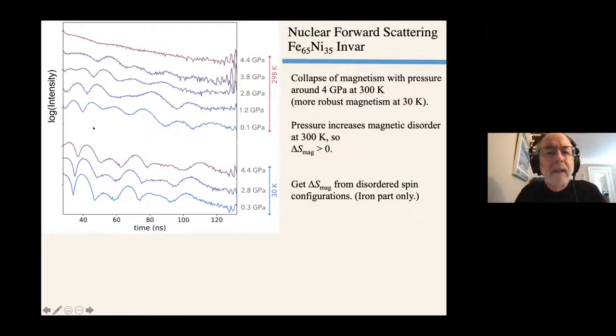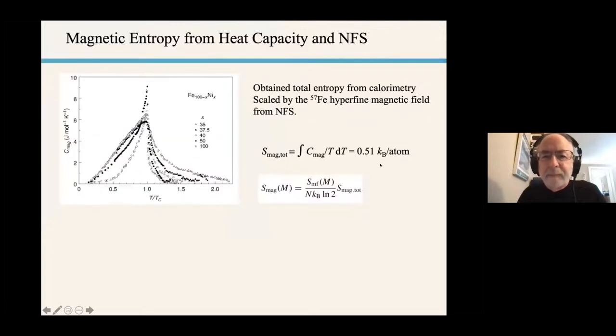At room temperature, the magnetism is decreasing. We've done more analysis of this. I'm not showing it here, but I just want to show you the raw data. You can see how this dip is increasing much more rapidly at room temperature and becoming pretty small at 4 gigapascals or so. The pattern of magnetism changes a lot. We're disordering the magnetic moments. So the magnetic entropy is greater than zero, and its change with pressure is opposite from that of the phonons. And we're only looking at the iron part. We have to do a little bit more for the nickel magnetism. We have some ideas on that, but it's not done yet.